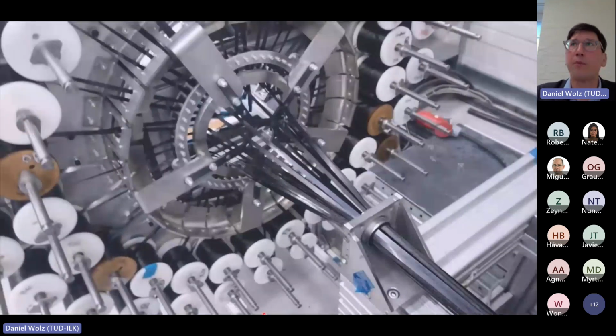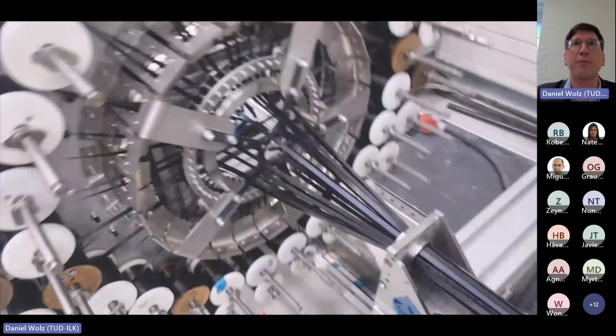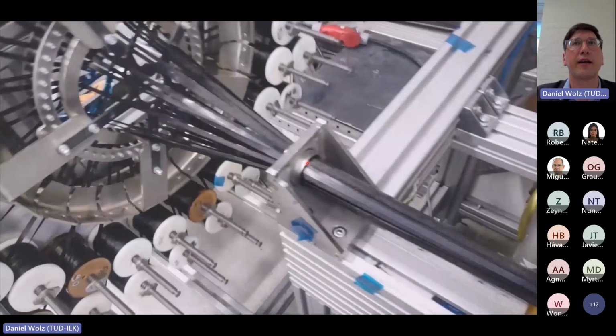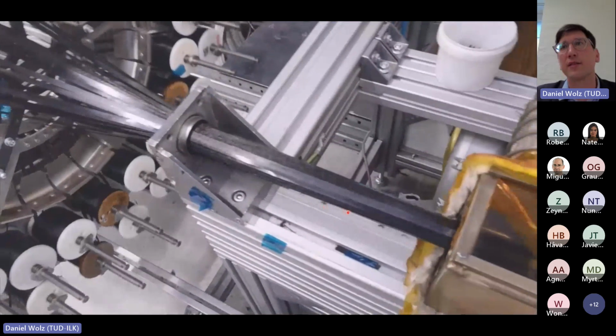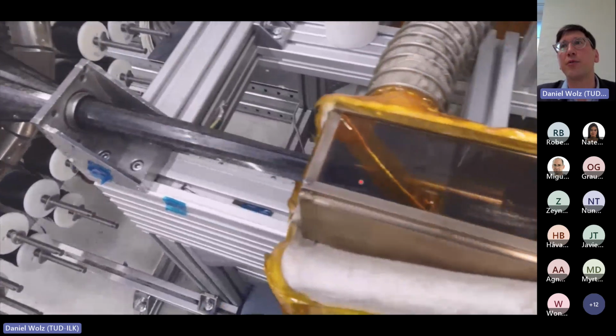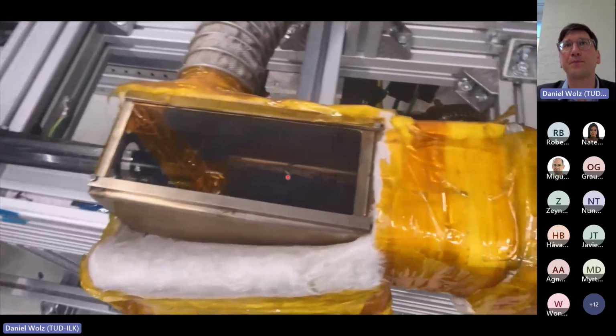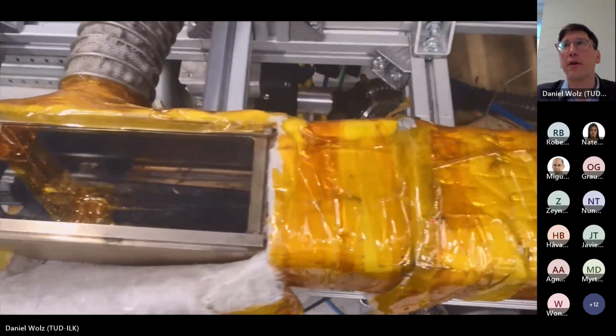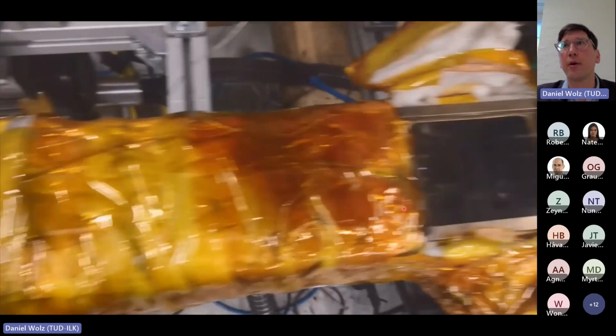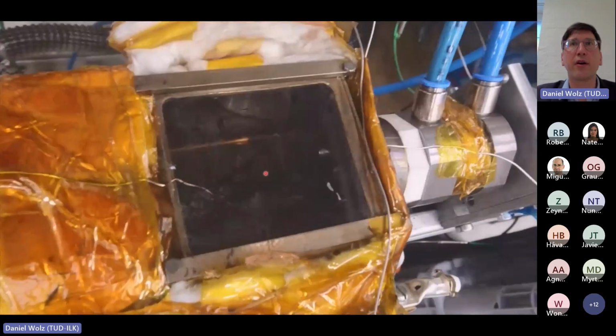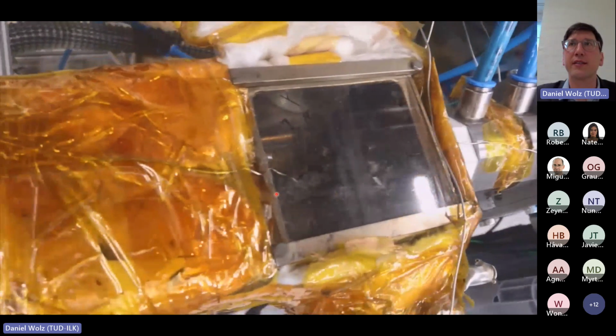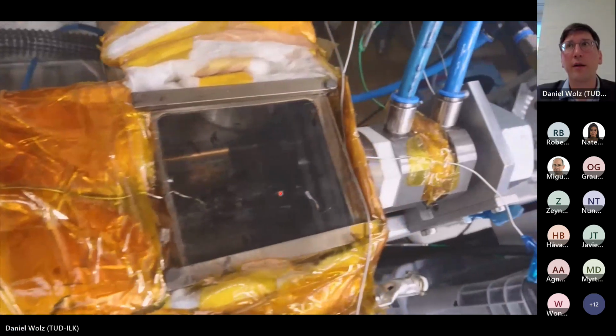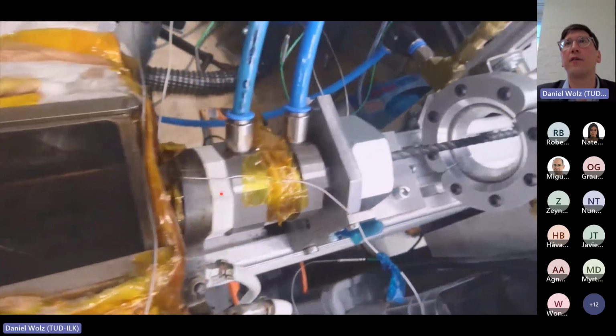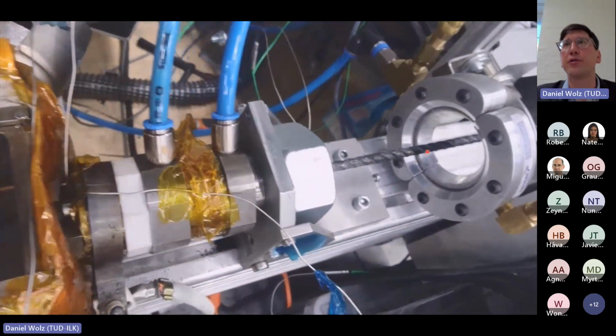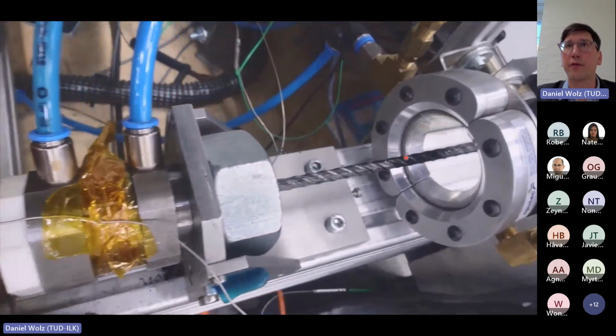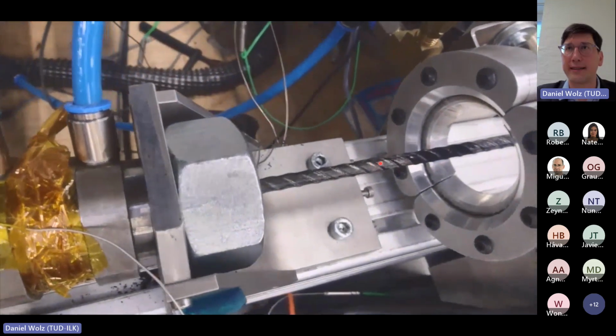I now hope the video will work smoothly. So what you see here is the collection device with the CF tapes, the heating device to heat up the carbon fibers, the cooling device and the molding device. This is the molding device where the polymer matrix is applied. Afterwards, the cooling device and the pultrusion of the fiber reinforcement rod itself.